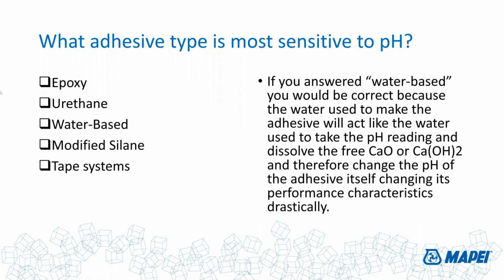So what type of adhesive do you think might be the most sensitive to pH? Is it going to be an epoxy, a urethane, a water-based adhesive like acrylic PSAs or an SBR latex, modified silane, tape systems? Hopefully you've answered water-based, because that's the correct term. They're going to be the most sensitive to the pH of a concrete slab because they have water in them. And the water is going to obviously help disperse what was in the adhesive, but it's also going to dissolve what's on the surface of the concrete slab.